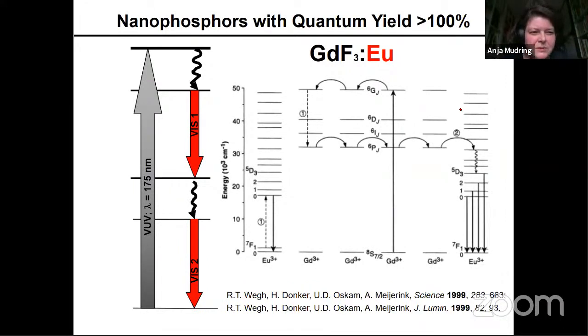This process was first described by Andries Meijerink, and he stated that for this process you need high quality single crystals, because he believed that the surface of the particle would lead to radiationless decay. So you would simply take the energy of the excited state, and because the surface is connected to something, you have organic material, for example, on the outside, that would transfer the energy to the organic material, excite OH, NH, CH bonds, and that would lead to a radiationless decay.